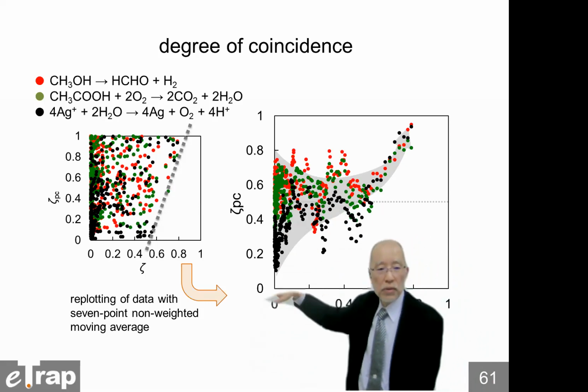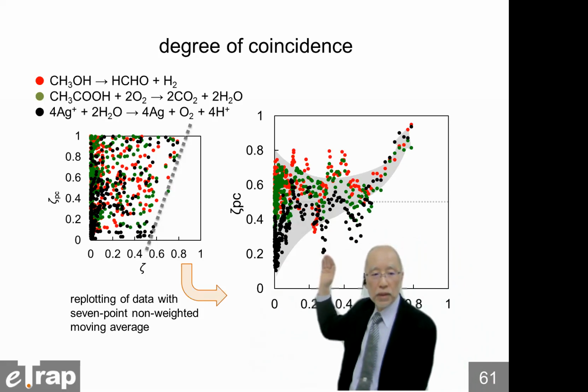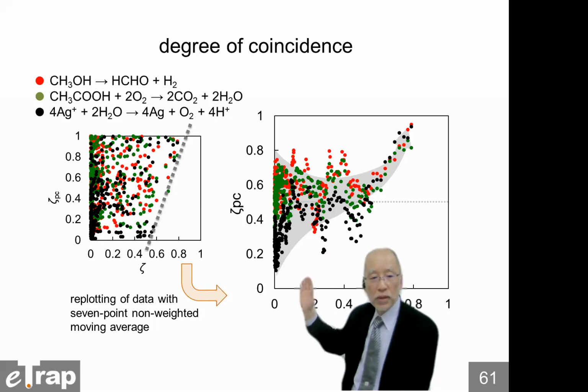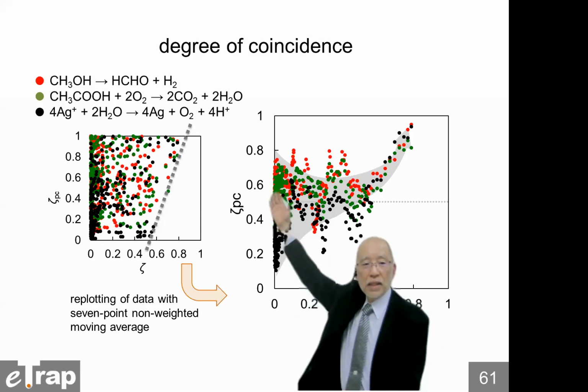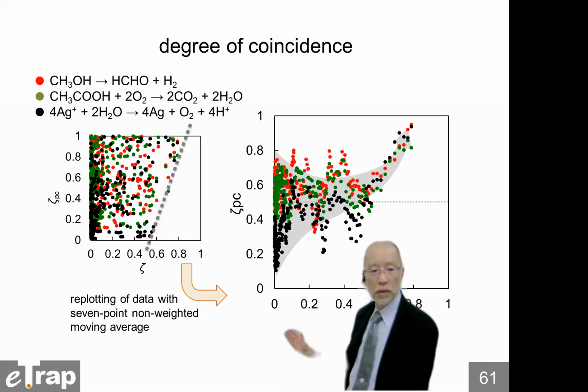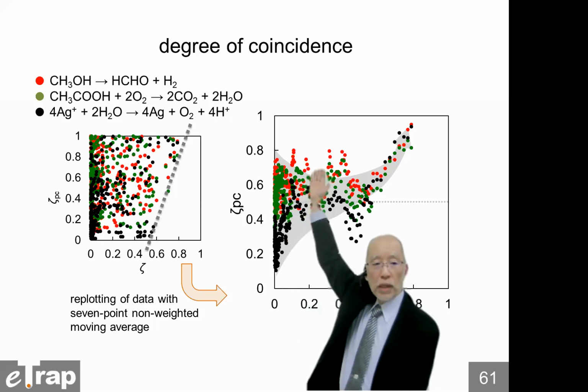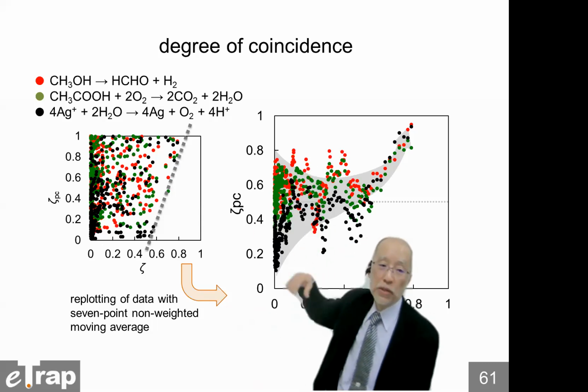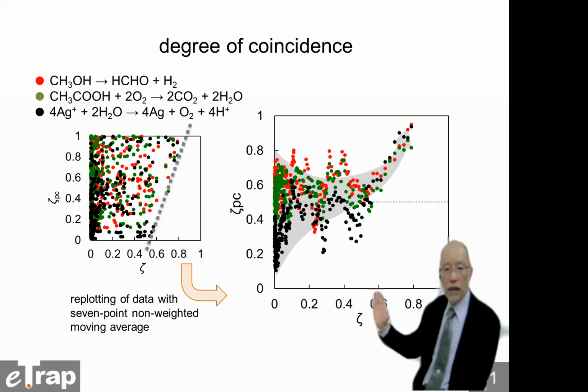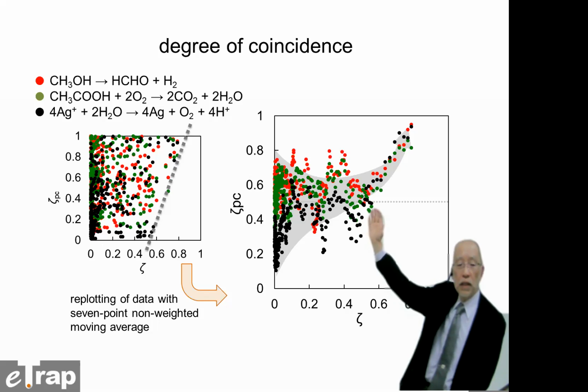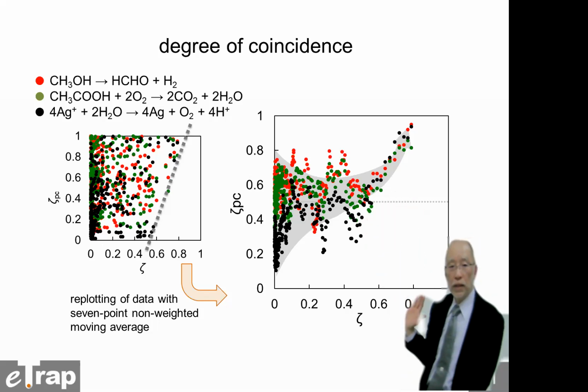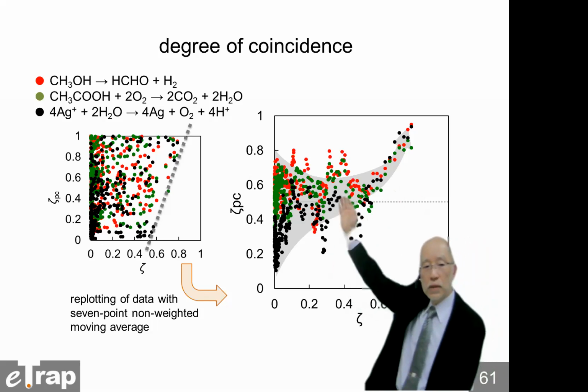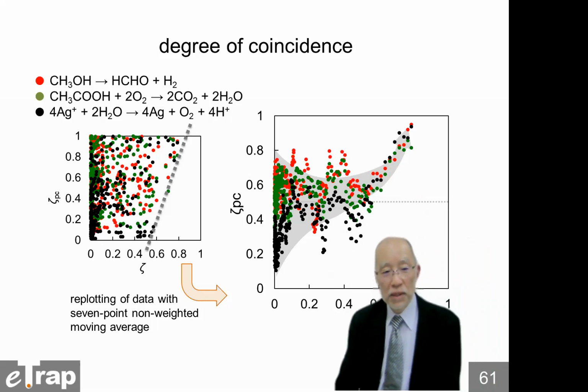And this is averaging. So therefore, at this position, for example, this black plot for oxygen evolution is very low. One pair of titanium oxide with a degree of coincidence of about 0.6 gives a very low value, and this pulls the other data to the lower side. And for this red one, at a degree of coincidence of about 0.1, a sample pulls up the other samples. So anyway, that is so much scattered. But if the degree of coincidence is higher than 0.6, the degree of coincidence of photocatalytic activity is increasing. And at 0.8 or 0.85, the degree of coincidence of photocatalytic activity becomes almost 1. That means the same photocatalytic activity.